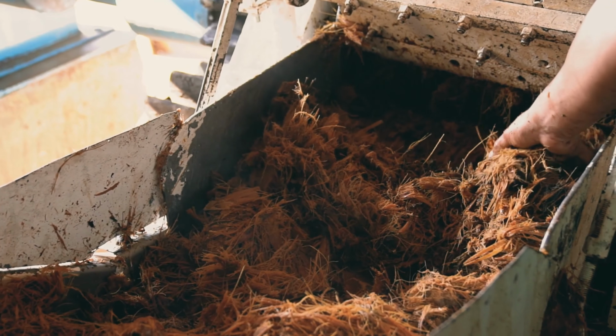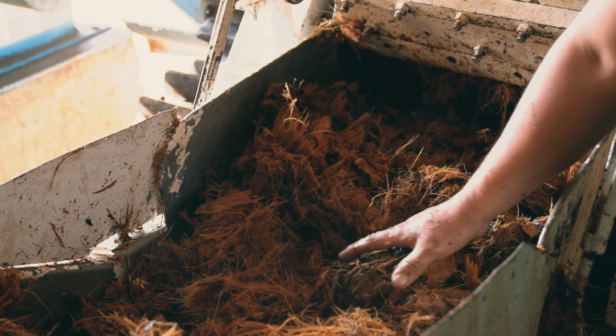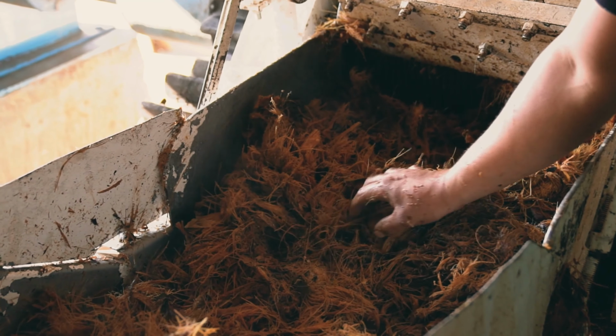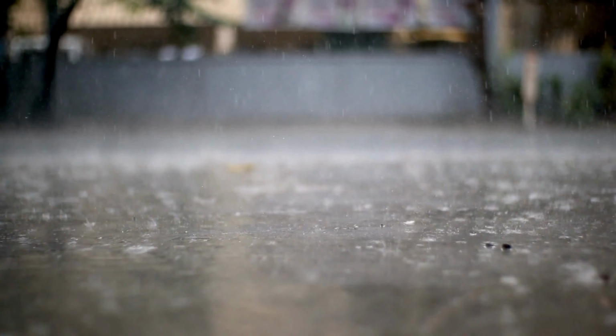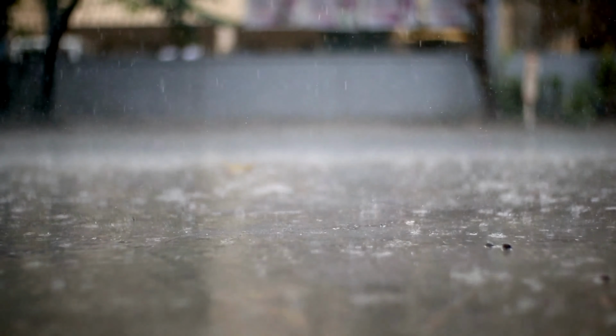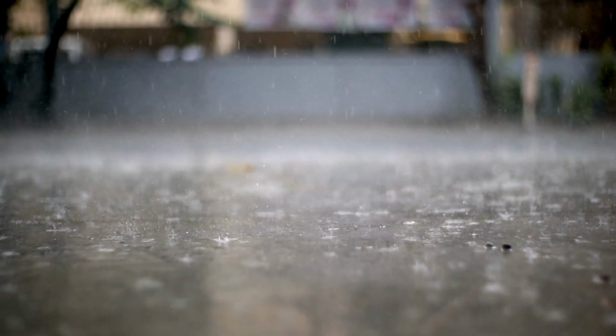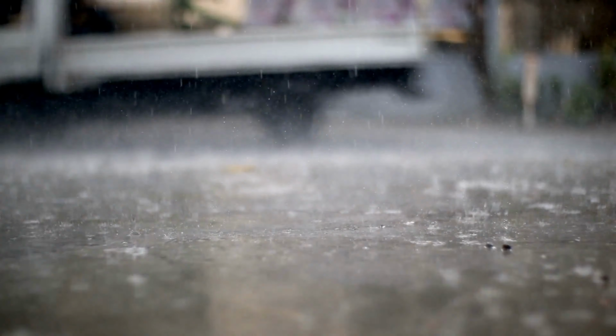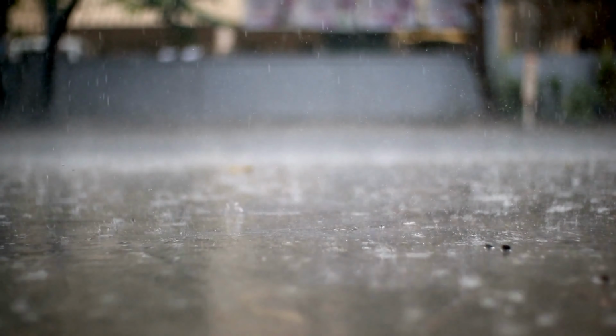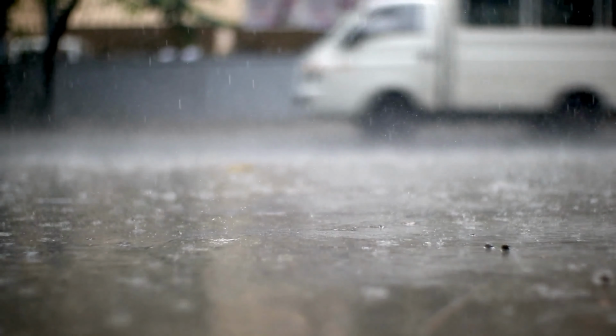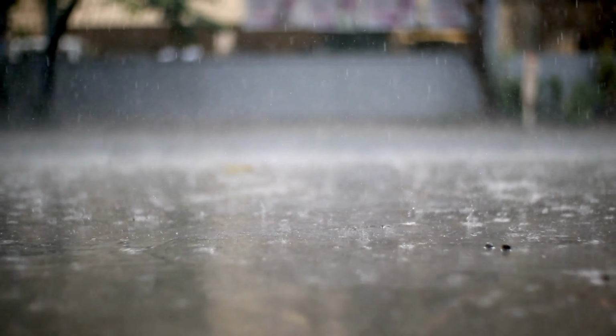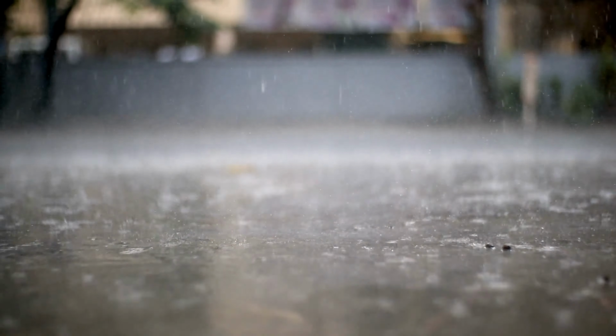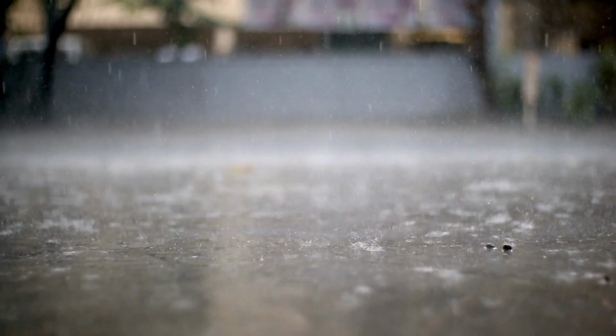The hurd, the woody core of the hemp stalk that makes up the bulk of the material, is organic. It is plant matter. The lime binder is highly alkaline, and that alkalinity is genuinely protective. It resists mold. It resists pests. This is why hempcrete has a reputation for durability, and the reputation is largely deserved. But under prolonged exposure to moisture, the hurd can degrade. There is research where hempcrete samples were cycled through immersion, freezing, and drying over and over. The porosity of the material increased as the microstructure changed, and the compressive strength went down. So did the thermal performance.